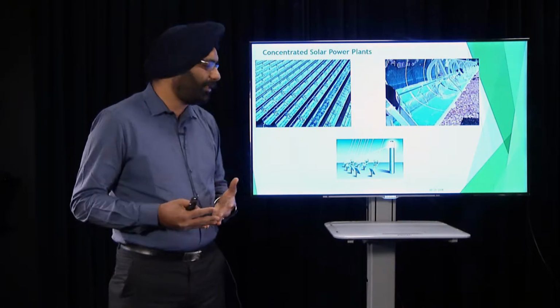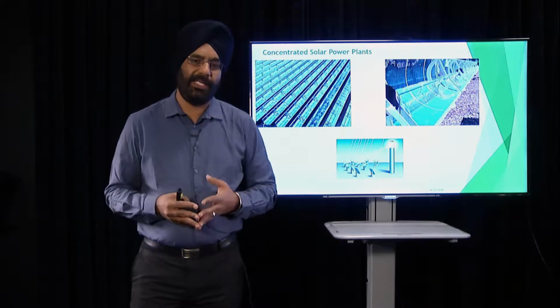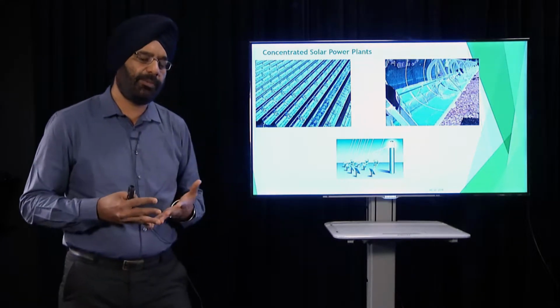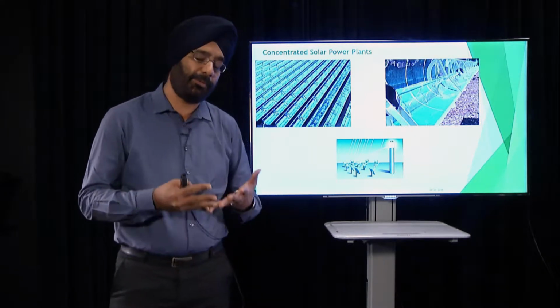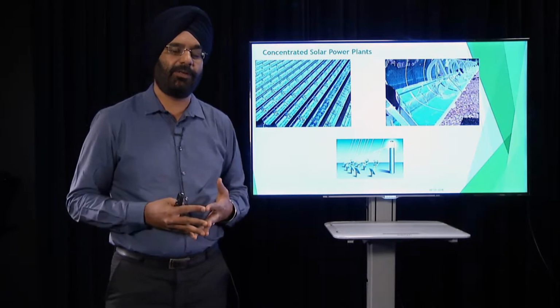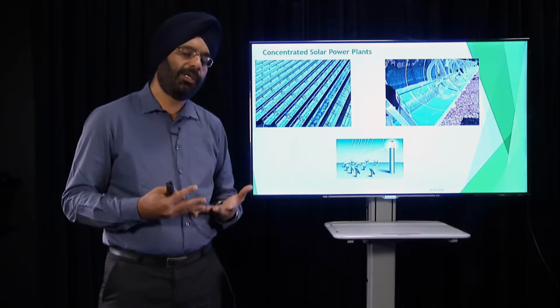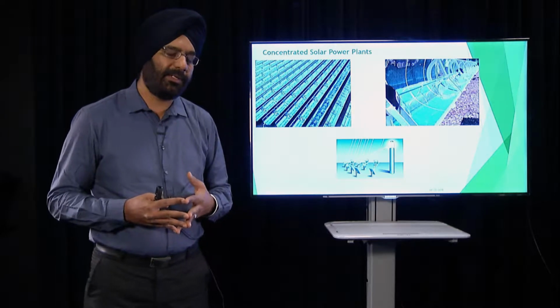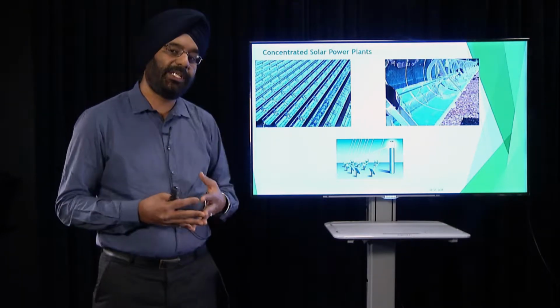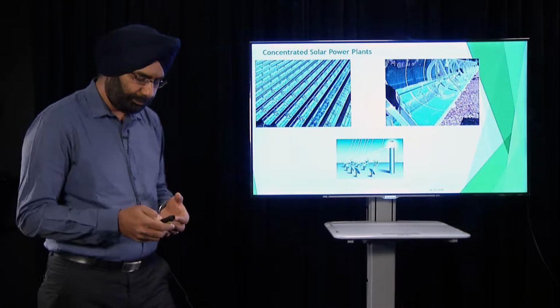With this technology, you can heat it to a much higher temperature than what you can achieve with the parabolic trough, so probably 600, 700, or even 800 degrees C. So that's what the central power receiver can do. It can provide you higher temperature.